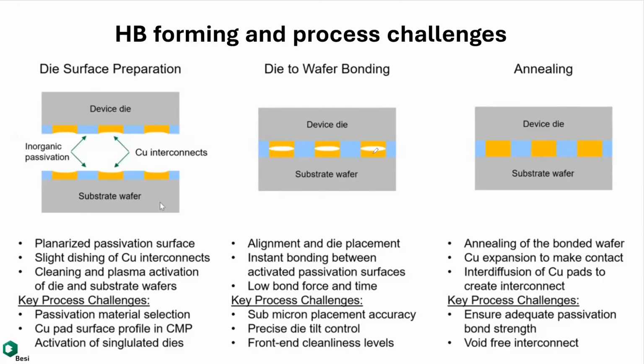And after that, you've got to get rid of this void. You anneal it at a certain high temperature, 150 to less than 300 degrees. Hopefully you can anneal all the voids off. Sometimes it's hard to remove them 100%. So if there's a little bit of void, that's probably okay, as long as you don't impact the integrity of the final results, such as the shear strength and all kinds of mechanical properties after you anneal.